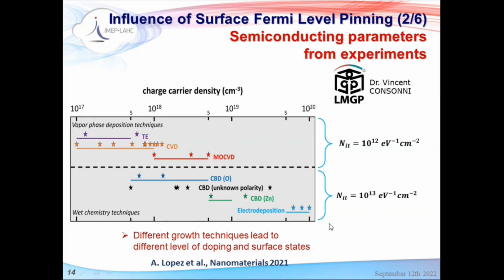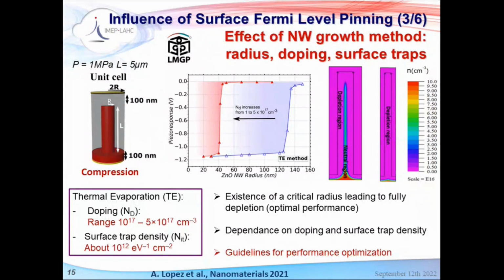So what we have done in the recent research is to include these doping levels and these real values of traps to see what the effect is on the real devices. So here I show you just one example, considering thermal evaporation. So you have the values of doping and surface traps. And in this case, we fix the length of the nanowires to a certain value, and we play with the radius. So I show you the potential that is produced under compression, as a function of the radius. The blue curve is for low values of doping in this range, and the red curve is for high values of doping levels.